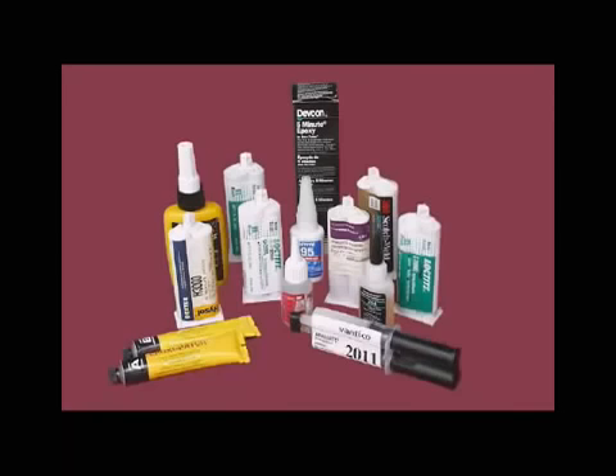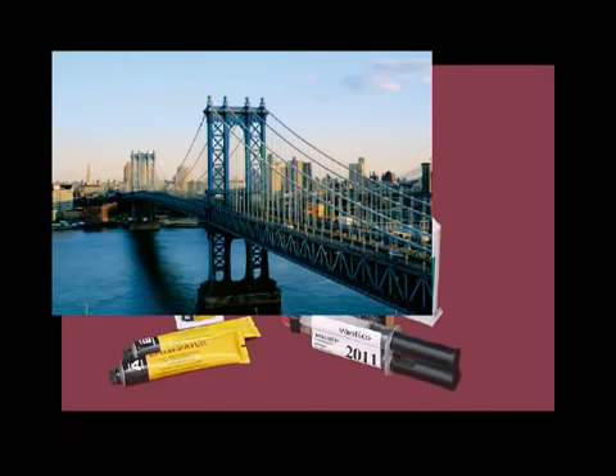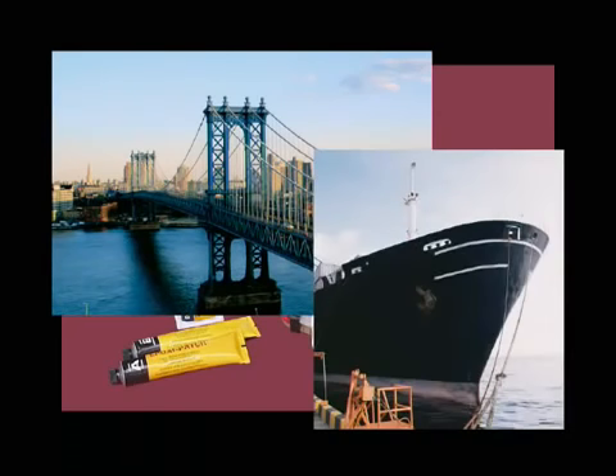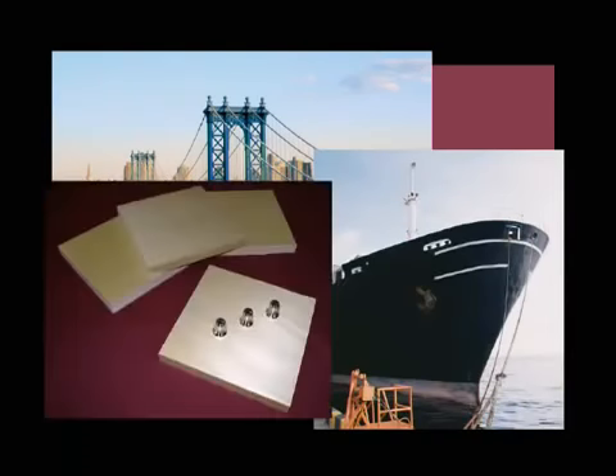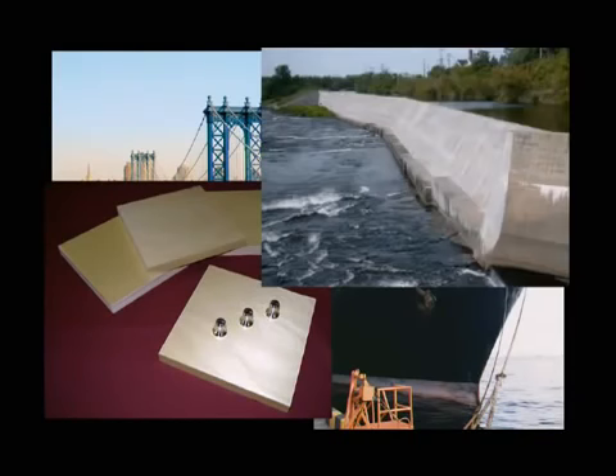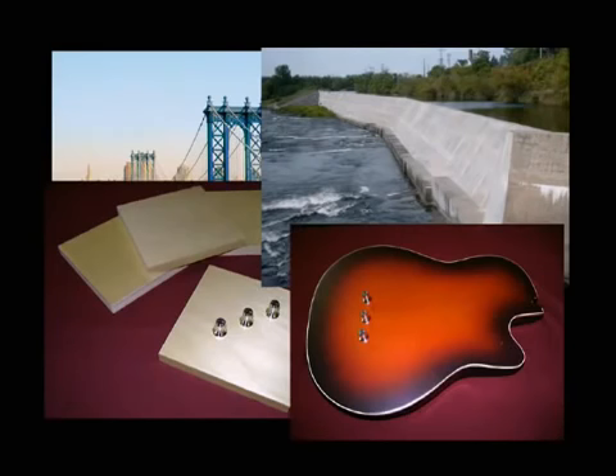Having selected the pull-off tester to be used, the next step is to identify a suitable adhesive for bonding the dolly to the coating. When selecting an adhesive, it is important to consider the expected bond strength and the nature of the coating and dolly. Specifications for most coatings are typically less than 1,000 psi. Thermal spray coatings are tested higher, though new standards quote acceptance levels at 1,000 psi or less.